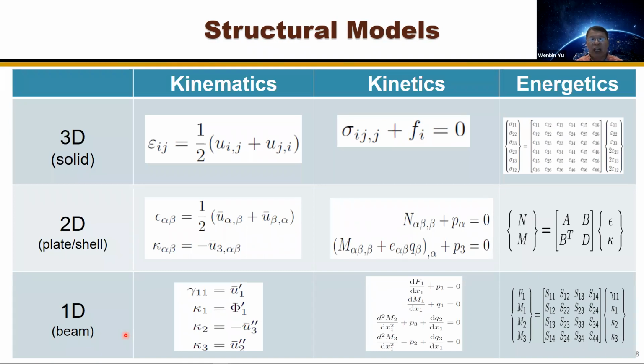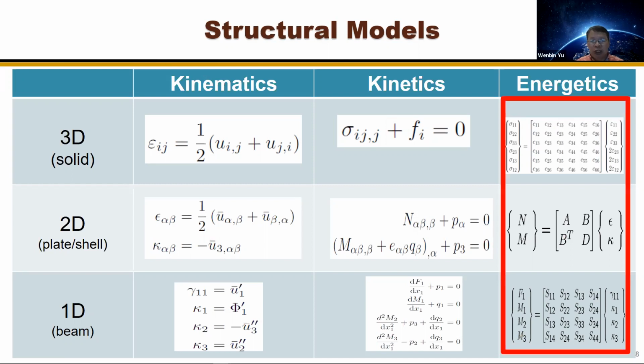And if you're familiar with continuum mechanics, for each structure model, we have 3 parts of equations: kinematics, kinetics, and energetics. Energetics is also called constitutive relations. And the kinematics and kinetics will remain the same, no matter if it's made of composites or not. What will be different is the constitutive relations. And here I only use linear elastic behavior for illustration, and it can go nonlinear. And what I have to point out is that for composites, particularly anisotropic heterogeneous materials, the stiffness matrix could be fully populated. For example, for the beam theory, we all know the EI, GJ, EA, this kind of beam constants. But for a composite beam, we could have a fully populated stiffness matrix. All the deformation modes could be coupled.